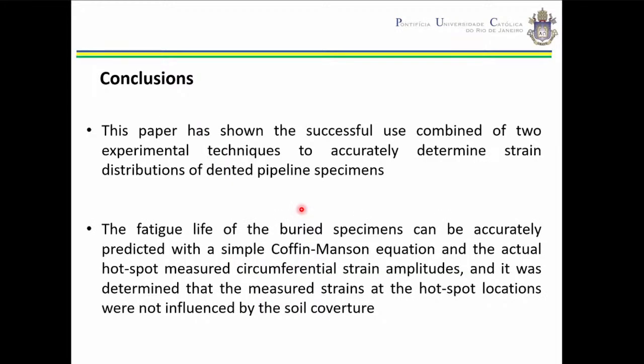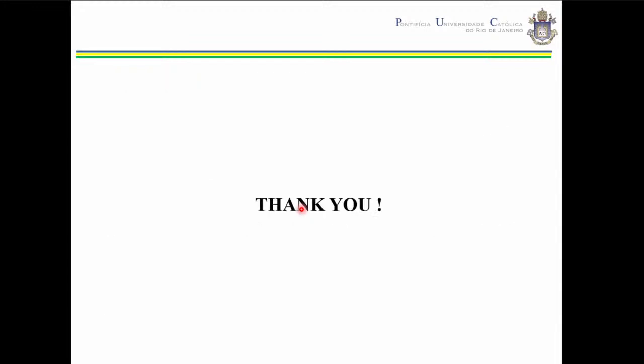The conclusion of this paper is that we combined two experimental techniques, digital image correlation and fiber optic strain gauge, and we were able to predict the life of the buried specimens with dents using a simple Coffin-Manson equation, and also the soil did not influence the life of the specimens. So I believe I have done all.